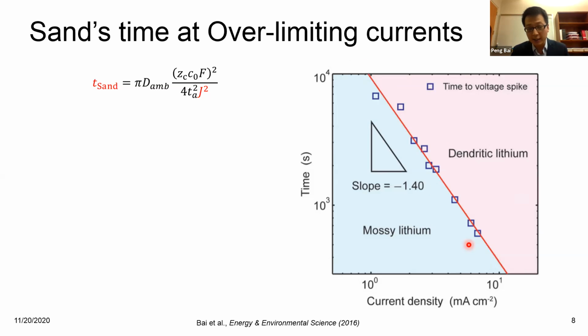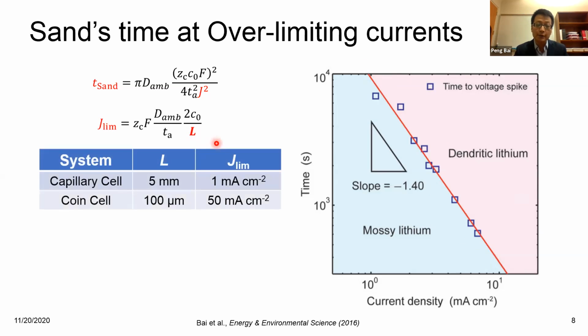But how high is high? One very important concept here is the limiting current. The limiting current, again, is a system property, but it depends on L, the distance between the two electrodes. For our capillary cells, we have a separation between two electrodes of around 5 millimeters. That means the limiting current is about 1 milliamp per centimeter squared, right? So even if we use a current density a little bit above 1 milliamp per centimeter squared, you will see this Sand time. You will generate diffusion limitation.